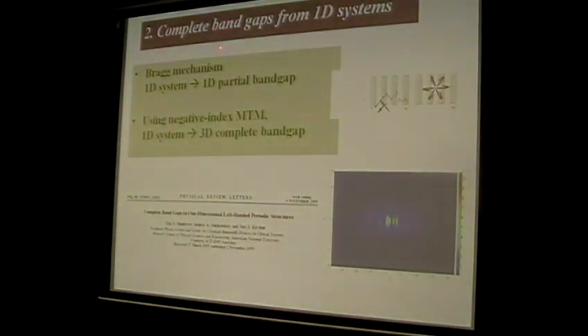There are some other interesting properties of this special reflection phase. For example, I think many of you are very familiar with the photonic bandgap effect, because the photonic bandgap is caused by the Bragg scattering. So you can imagine that a 1D system can only support a 1D partial bandgap. For example, this layer system must have a 1D partial bandgap, and for this direction, it does not support any bandgap at all. However, the picture changes if we use negative index materials. In this paper, our Australian group proposed that if you use negative index materials, you can have a 1D system like this support a 3D complete bandgap like this.